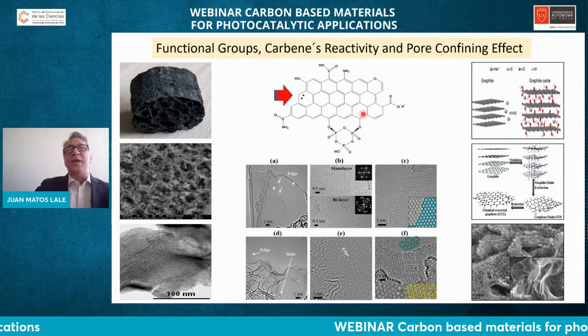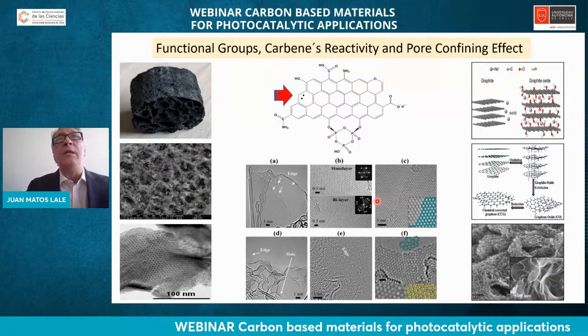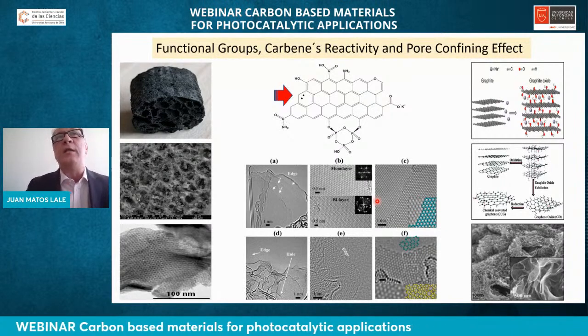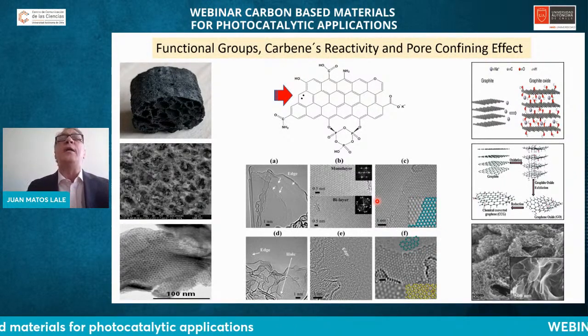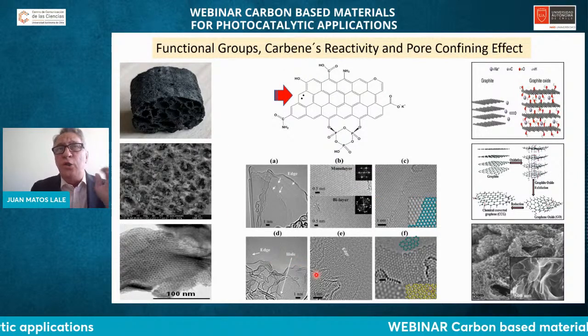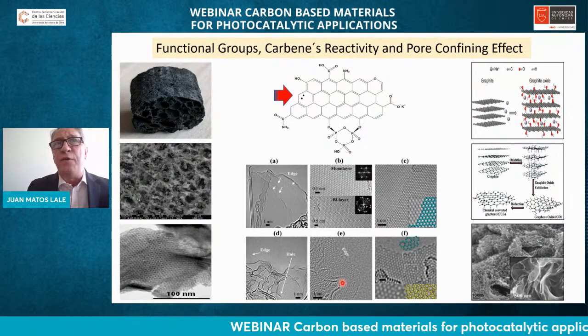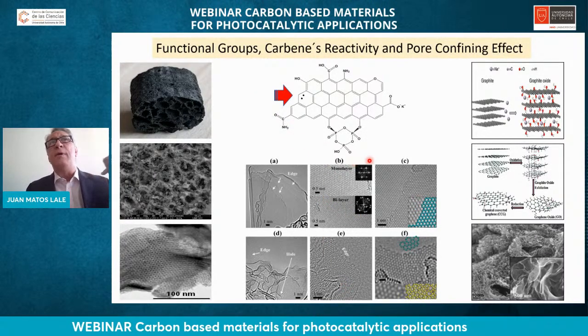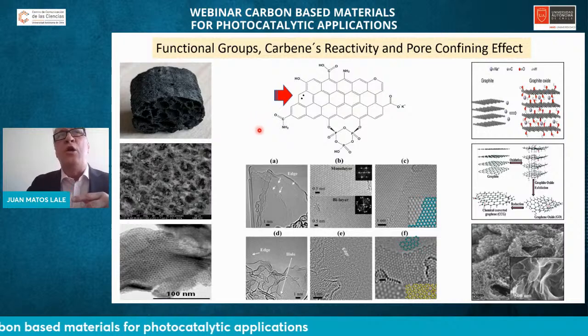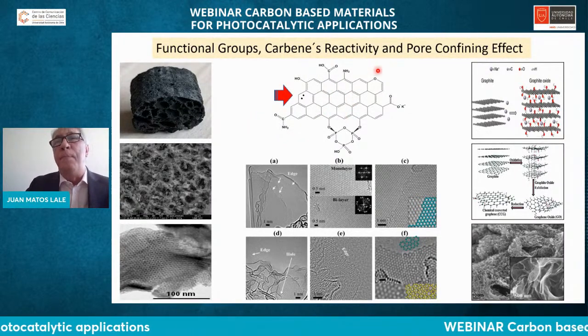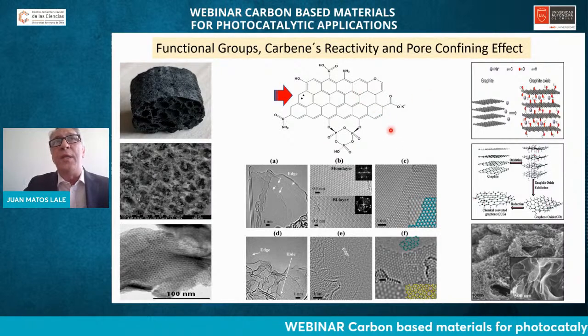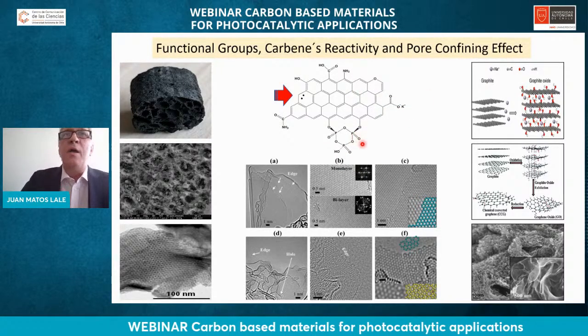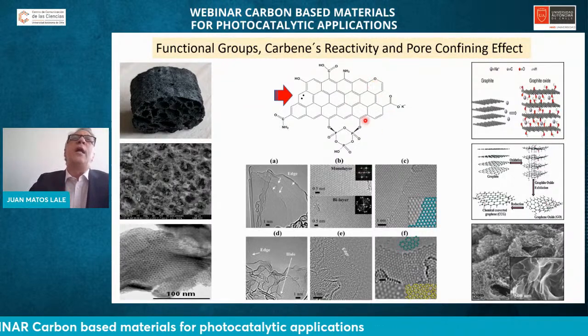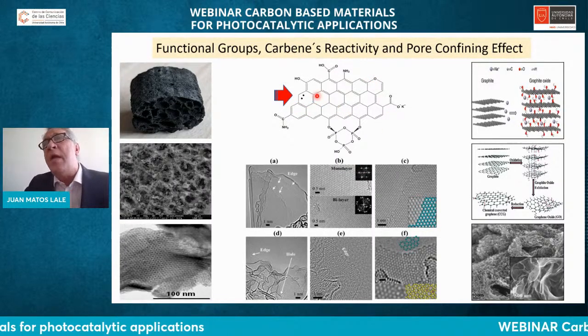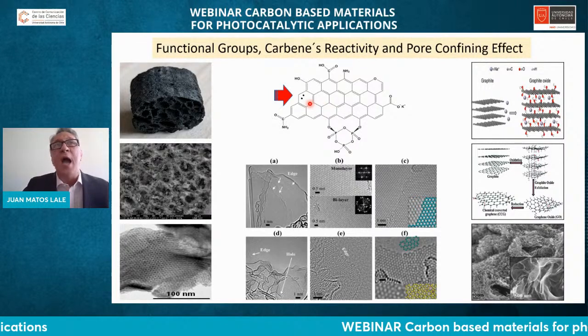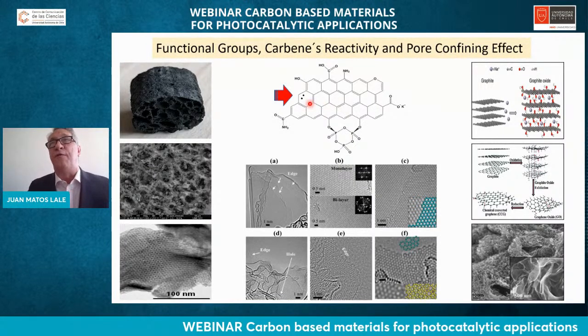You can see here also that the reason for the high reactivity of carbons, not only in thermal catalytic reactions but also intrinsically as photocatalysts, is due to several factors: topology, pore size distribution, high surface area, and in addition, it is relatively easy to control the functionality. We can include different kinds of interesting groups, for example nitrogen doping, potassium intercalation, phosphorus intercalation, oxygen intercalation, and at the same time we can control the formation of carbenes, which are very reactive and very useful species for photocatalysis.